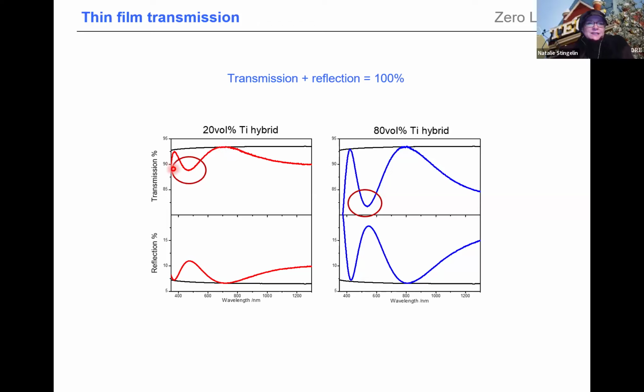And what is key is you have here this dimple, so you have a lower transmission. This is not absorption, this is not scattering. Why? Wherever you have a low transmission, you have a high reflection. So this just tells you the deeper those oscillations are, the higher the refractive index. These are not losses, and they're really easy to synthesize.